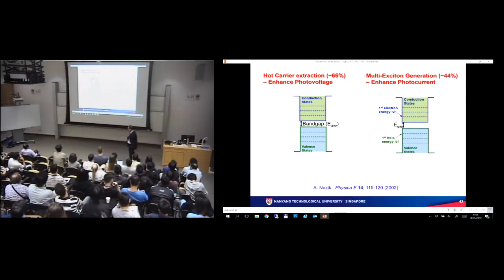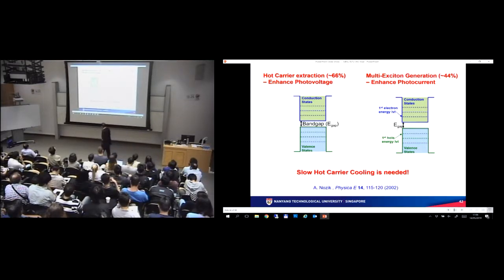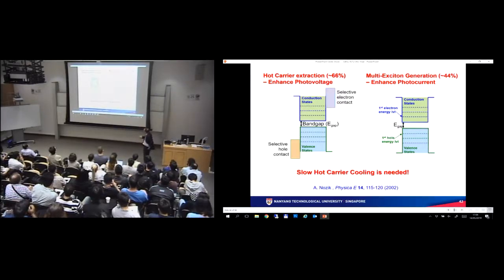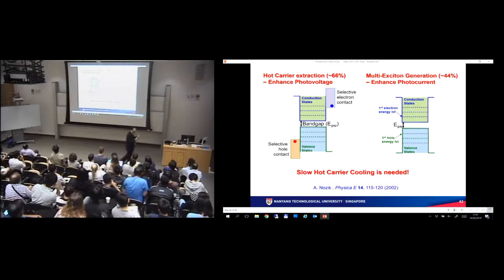Now, both these approaches share one common key criterion. You need the hot carrier cooling to be slow in order to make these two processes more favorable, both for extraction and for multiple exciton generation to occur. Now, what is hot carrier extraction then? Let me just illustrate this with a cartoon. The idea is you want to have selective electron or selective hole contacts. After excitation, before the hot carriers have a chance to relax, you want to extract them. And definitely having your hot carrier cooling be slow makes things a little bit easier. So that's the first concept.